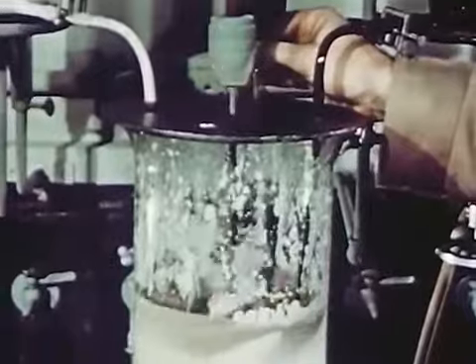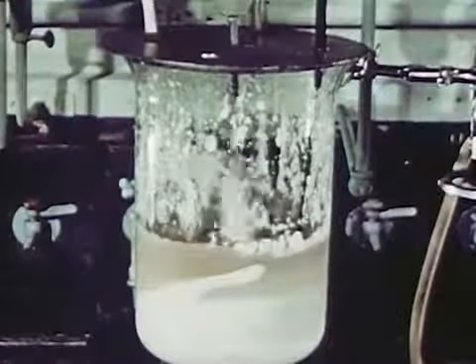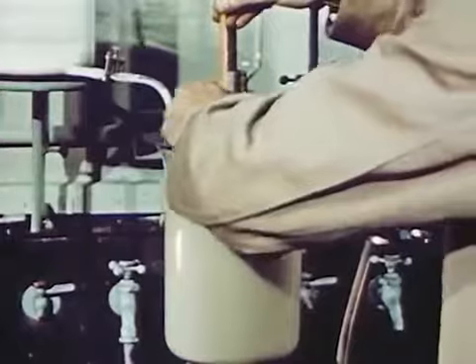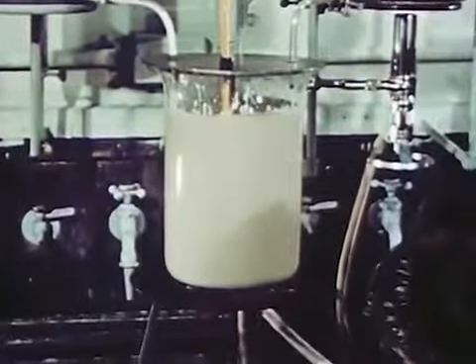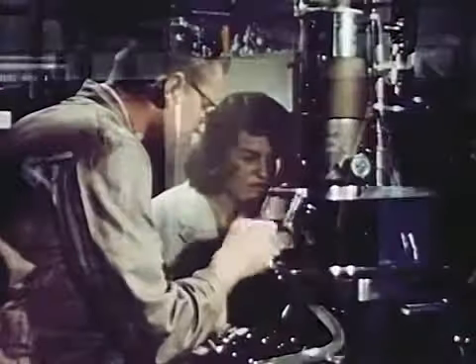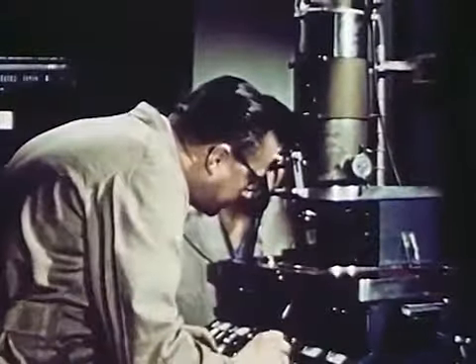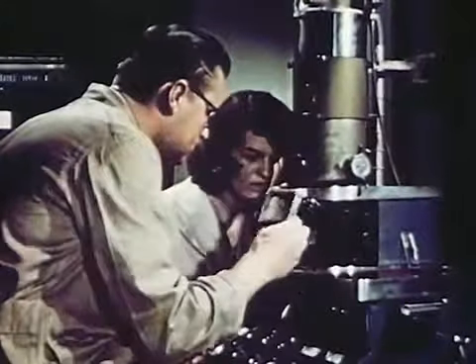The titanium solution is added to this calcium sulfate along with nuclei just before hydrolysis, so that the titanium hydrate precipitates and is deposited upon the calcium sulfate, forming a tight union of these substances, a truly coalesced composite pigment. This fact is established by the electron microscope, which magnifies the pigment particles on a scale comparable to enlarging a housefly to the size of the tallest building in the world.